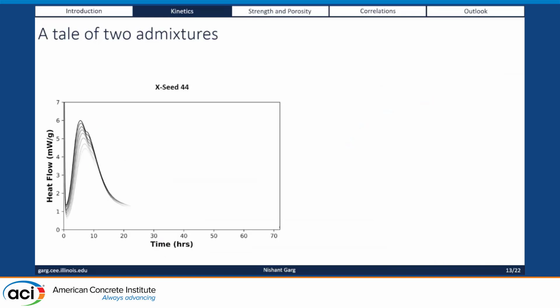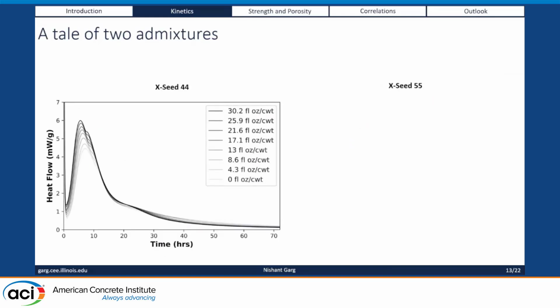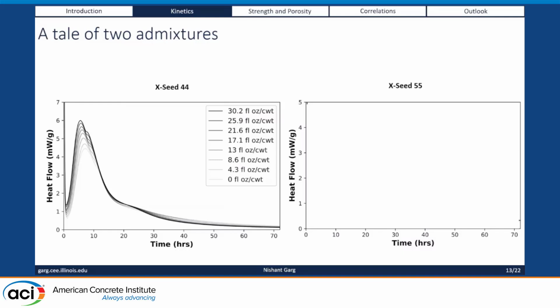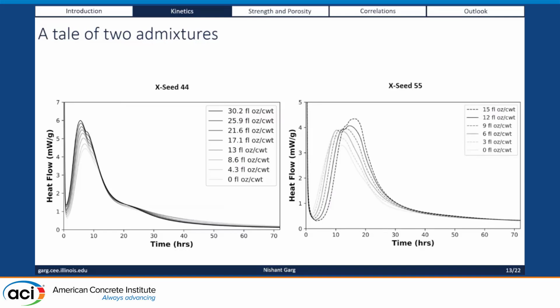If you look at the two admixtures here, you have the X-Seed 44 and the X-Seed 55. The interesting thing is these two admixtures actually behave slightly differently. One of them accelerates and one of them slightly retards the reaction, which is kind of interesting. What we understand is the reason is the amount of PCE and HRWR you have in them. But the cumulative heat is improved for both of them, which is good, because that's what ultimately matters from a strength enhancement point of view.